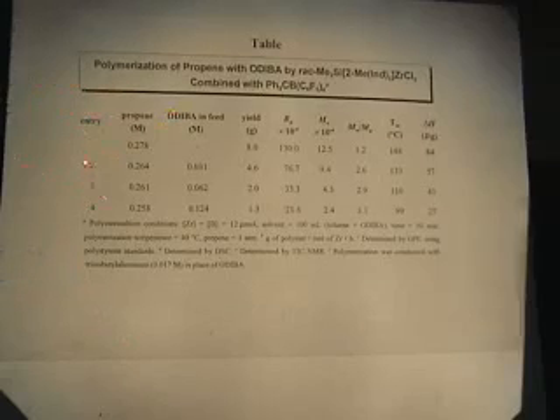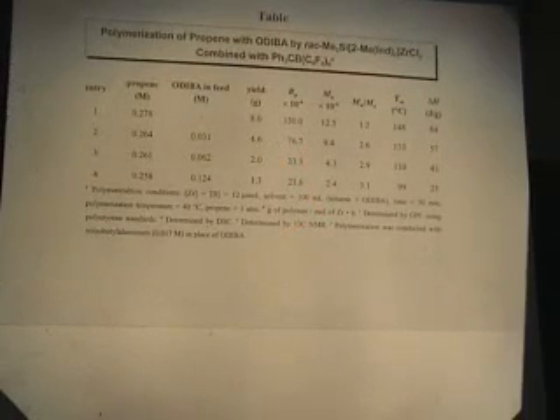This table shows the polymerization of propylene with the isospecific metallocene catalyst combined with trityl borate. The activity decreased dramatically with aluminum concentration in the feed compared with polypropylene. The number average molecular weight decreased with increasing aluminum concentration. It means chain transfer to aluminum occurs in this case. In the thermal properties, the melting point and heat of fusion increased with aluminum concentration. We can explain this phenomenon by the addition of ODIBA.